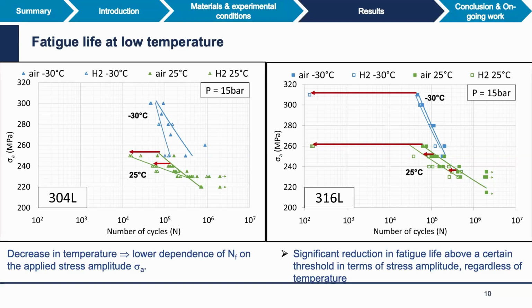And what we observe is that for the very long fatigue lives, we have almost no impact of hydrogen, but we need to apply stress amplitude above a certain threshold in order to notice a decrease in the fatigue life in presence of hydrogen, as indicated by the red arrows here. And you have the same here for the 316L. So here, presumably, we need to investigate higher values of the stress amplitude in order to highlight this phenomenon.